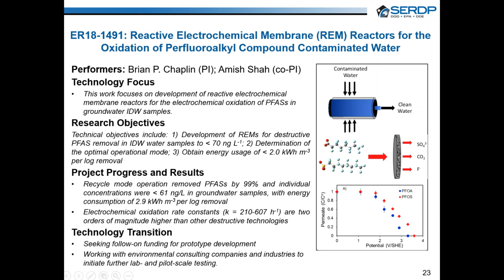The high rate constants reported in this study are the highest reported for electrochemical oxidation of PFASs, and the low energy consumption is much more favorable than other destructive treatment technologies, demonstrating the promise of the reactive electrochemical membrane technology for PFAS.